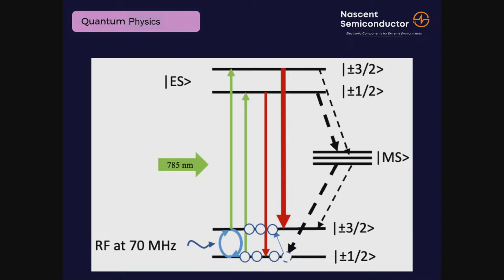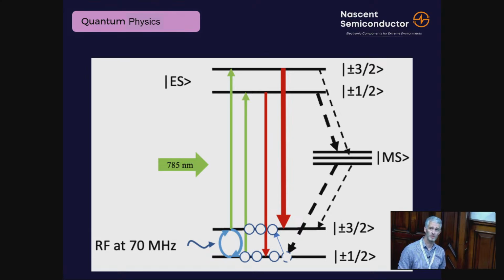Down at the bottom, you've got two energy levels, a spin half and a spin 3/2 energy level. And they're separated by a small energy that's resonant with an RF signal at 70 megahertz. We can shine a laser on this, a 785 nanometer laser, infrared, not much fun in the university because health and safety people really don't like you. And we pump all the carriers up to the top, so we put our defect into the excited state marked by ES, and then it relaxes back. It's an unstable dynamic equilibrium.